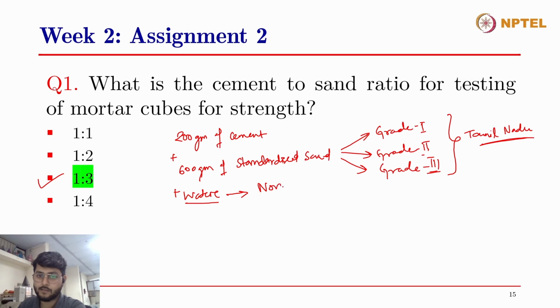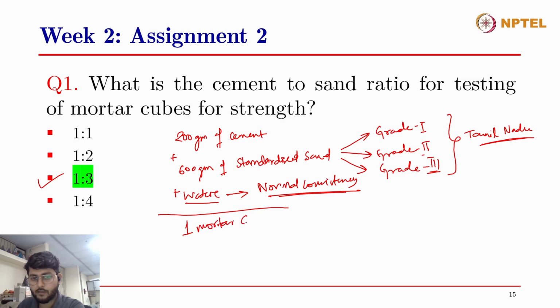I'm not sure exactly, but yes. So this standard sand has to be procured from that region of Tamil Nadu, and it has to be taken in equal amounts from grade 1, grade 2 and grade 3, plus water, which can be calculated from the normal consistency test. When we mix all of these constituents, we can produce only one mortar cube. So depending on the number of mortar cubes you want, you can't just make a big mix. You have to take these proportions and prepare each mortar cube separately: 200 grams of cement, 600 grams of sand, and water from the normal consistency per cube. These are the different ways the Indian standards have specified to have consistency in the results of the strength test of cement.